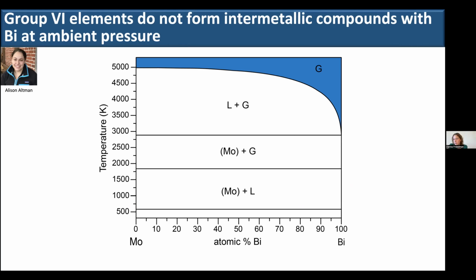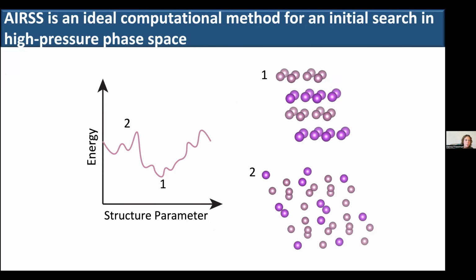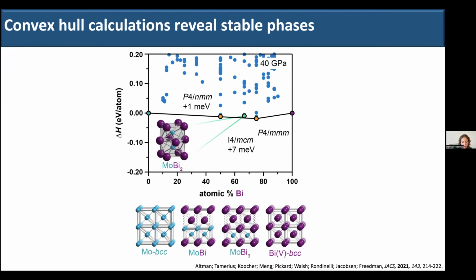So if we want to do this, we could go in blind the way we did for iron bismuth. But actually, in the intervening years between creating that compound and where we are right now, there's been a lot of amazing theoretical work on creating programs. One is the AIRSS computational method, where effectively we're sampling phase space and looking for local minima. And in applying this to this system, we were able to map out a number of potential compounds. And so what we're looking at here is the atomic percent of bismuth and the enthalpy.